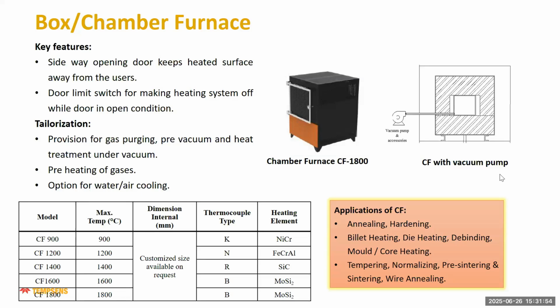We have different models, like CF 900, which can go up to 900 degrees centigrade. Sizes can be as per the requirement. The thermocouple can be K type or N type, and the heating element can be nichrome. For CF 1200, we have a temperature up to 1200 degrees centigrade. The thermocouple type will be N, and the heating element will be FeCrAl. For CF 1400, we have a temperature range of 1400. The thermocouple type will be R, and the heating element can be silicon carbide.